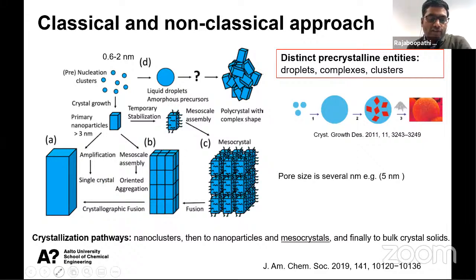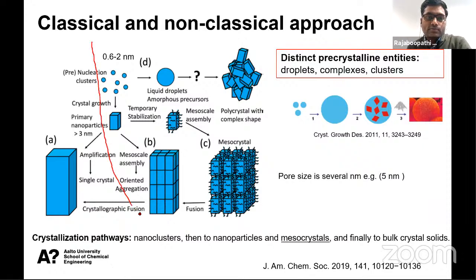So to further explain what is classical and non-classical, if you assume the right side is non-classical, and this is classical. So here, this is the nucleation cluster. In the classical crystallization, once the nucleation cluster reaches the critical radius, you will get a nucleus. The nucleus will further grow either by atom-by-atom addition or layer-by-layer growth. You will get a bulk single crystal. If you cut or break the crystal, the cleavage plane is very clean. It is a classically grown crystal.